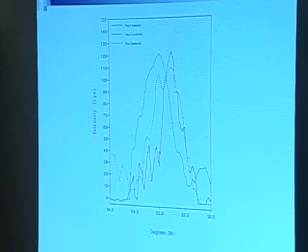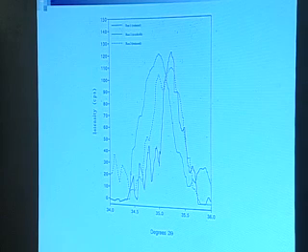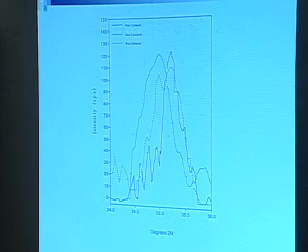This is an experiment done by Jonathan Chun. This is a real tour de force. This is not easy to do. First of all, X-rays don't like to go through water. They get absorbed and don't make it out of your cell. And second of all, we have a very thin layer of nickel ferricyanide here, even though we bulked it up as much as we could. And third of all, you have to have it in a cell, so you have to have an X-ray transparent cell. And then you have to be able to fit this all in your diffractometer. And remember, the thing about a diffractometer is it rotates. I'm looking at an angle down here versus a scattering intensity. And there's all these wires and whatnot that can get tangled up.